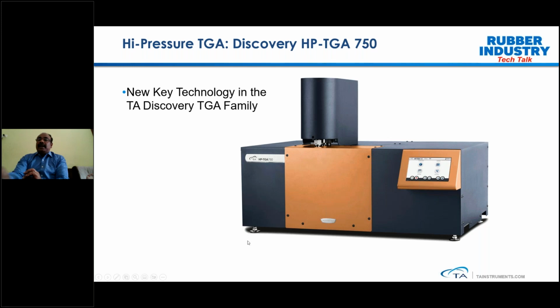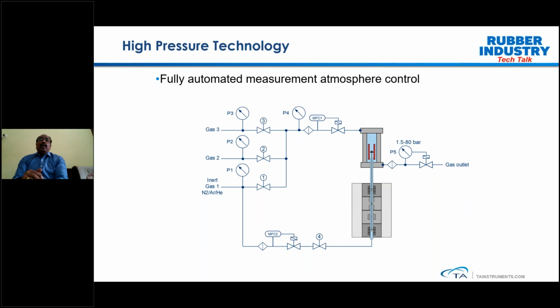This is offered by TA, an advanced, patented technique, where we are using a unique technology called magnetic suspension balance, which facilitates not only studies at elevated pressure, but you can also use a corrosive atmosphere. You have a pre-gas mixing solution that will connect to a reactive gas system, and you can create a very corrosive atmosphere, which many times is not possible on the standard TGA. So this is a very superior technology.